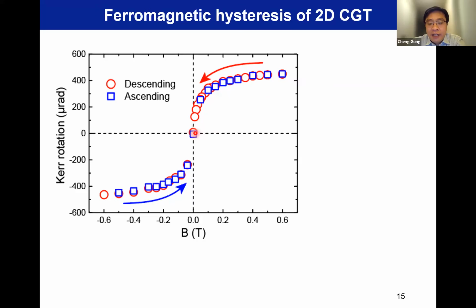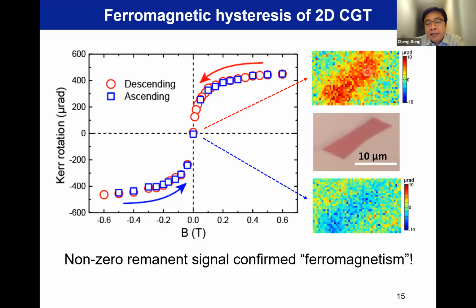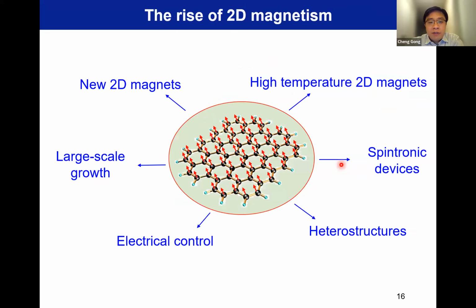That decides whether this is a ferromagnetism or not. So by looking at these 2 data, actually these 2 data are extracted from a scanned Kerr rotation image. You can see when I withdraw the field from positive field or negative field, the remnants are there, non-zero, opposite in sign. So this is a clear evidence. This non-zero remnants shows this is a ferromagnetism. So these 2 parts of data, temperature-dependent data and magnetic field-dependent data, clearly confirm this is a 2D ferromagnet. And now I think you all see this field is really rising up quickly towards different fronts.